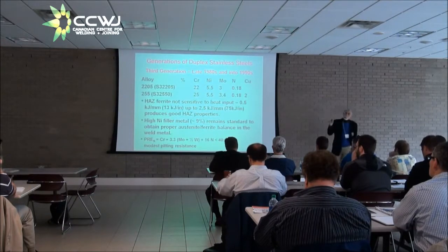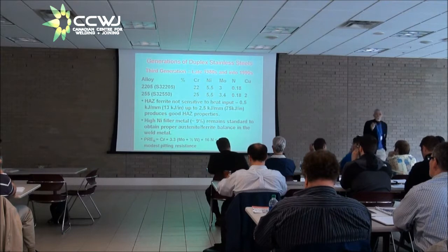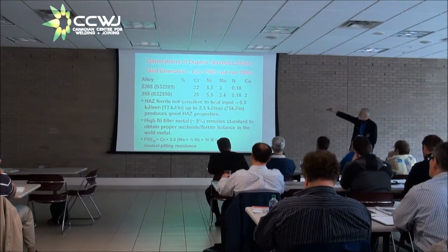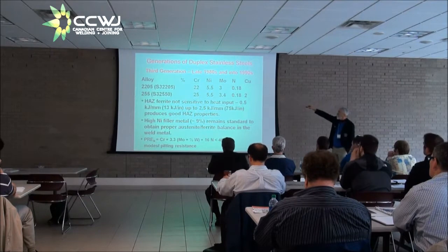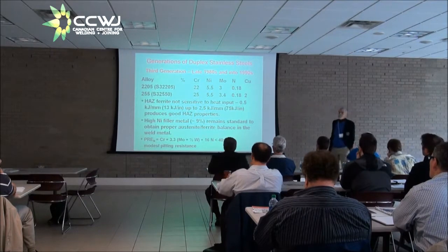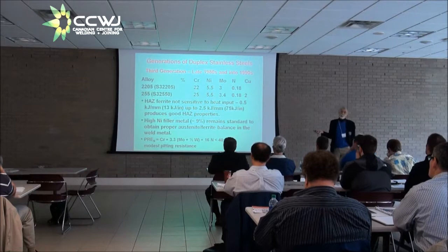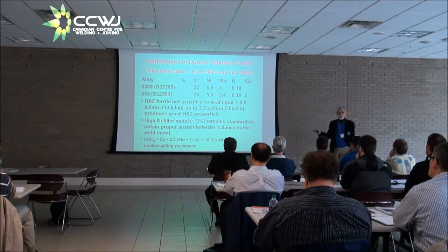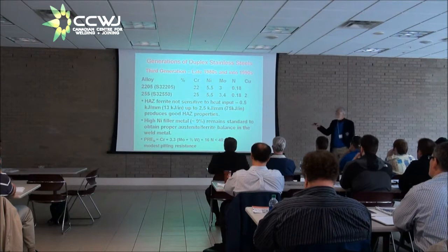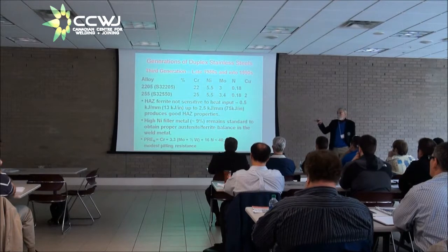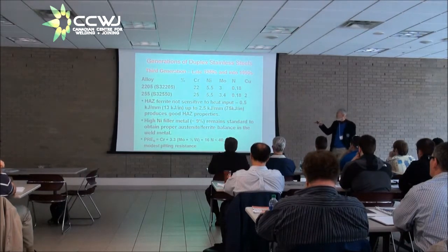But this brings us to the third generation of duplex stainless steels. And 2205 appears in this generation as well. But now it has a new UNS number. Instead of S31803, you see S32205. The ASME code in year 2000 redefined the 2205 base material by this UNS number S32205. The minimum nitrogen content in that alloy is now 14 points instead of 8. And that has a big effect on the weldability.